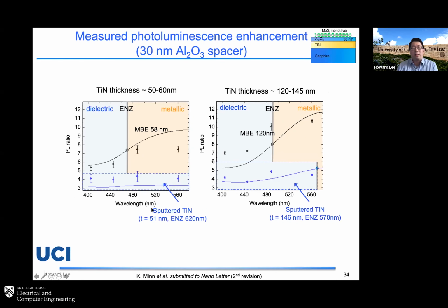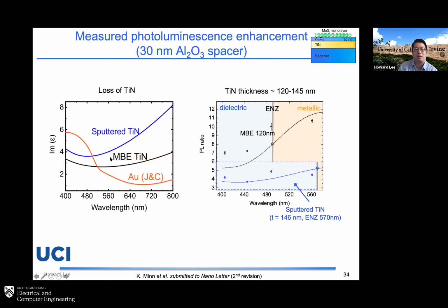But now, if you take a look at another titanium nitride ENZ thin film, which is a sputtered thin film with a longer ENZ wavelength, you find your PL enhancement is much weaker than the MBE-grown titanium nitride, maybe a few times smaller. There are two reasons for that. One is that it is actually on the dielectric side. At the same time, the loss of this material differs between the sputtered thin film and the MBE-grown one: the MBE-grown film has much lower loss. That's why you have a much stronger PL enhancement, and also why you can enhance the absorption on the monolayer more strongly, so you have a stronger excitation enhancement contributing to the PL enhancement.